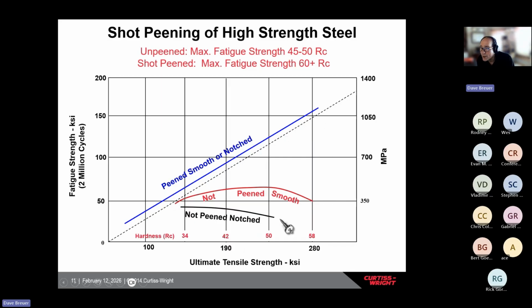But now, in this example here, it shows that some of your optimal hardness might be around 45, 50, because this has a good blend of ductility and strength. However, when you shot peen something, which is the blue curve, I had mentioned that as the part gets higher strength, the proportion of the amount of compressive stress you get is proportional to the strength of the surface. So as the surface is getting harder and stronger, you're getting more compressive stress from the shot peening.